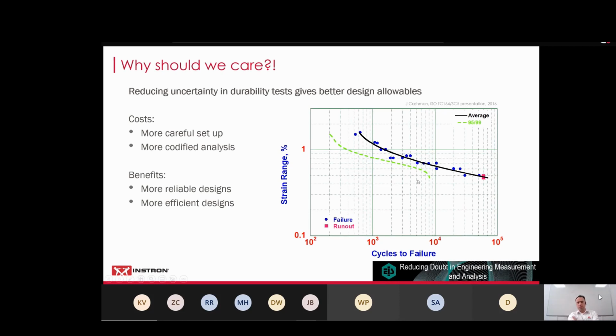So you look at the little graph here, and we've got a fatigue life, an SN curve, well, an EN curve because it's strain range, and you can see the scatter. Now, what we have to do when someone is designing an aircraft structure or something, they have to take a 95-99 confidence limit, which is the green line here. Apologies if that isn't very clear on screen. And that's actually quite well to the left or, if you prefer, quite well down from the average curve.